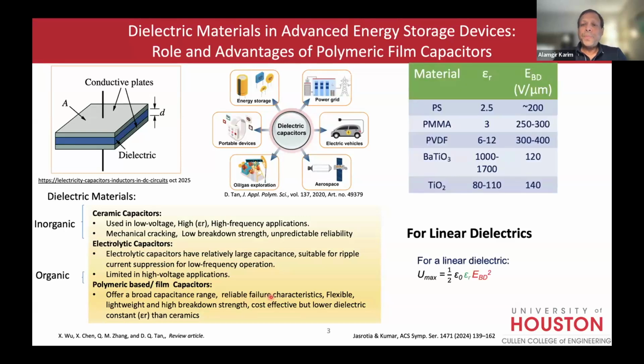So here is a table of materials. What really matters, as you can see in this equation, is that the energy density is a function of permittivity, or dielectric constant, and the square of the breakdown voltage determines the maximum energy you can store. So there's two quantities, dielectric constant and breakdown voltage. If you look in this chart, you see polymers have low dielectric constant, so the permittivity is low, but the breakdown is high. Same for most of the other polymers.